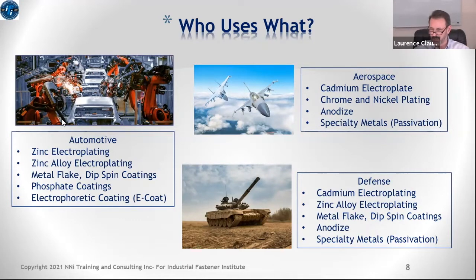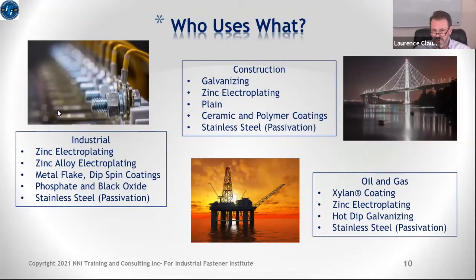The addition in the defense industry, though, and we'll talk about this a little bit later, is that they seem to be making greater headway in eliminating or replacing CAD, and they seem to be doing that with zinc alloy electroplatings and metal flake electroplatings. On the industrial side here, again, industrial just covers a huge wide range of different options. So again, this is not all inclusive of every finish, but we do see a heavy concentration of zinc electroplating, metal flake platings, phosphate and black oxide coatings, and again, use of stainless steel in industrial applications.